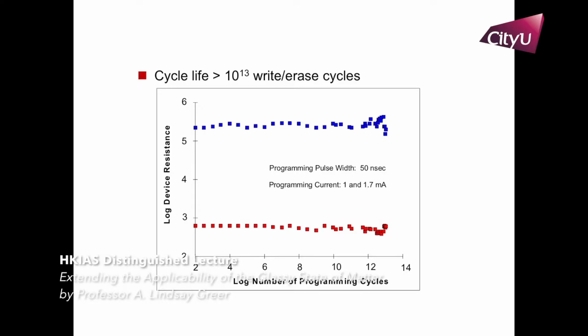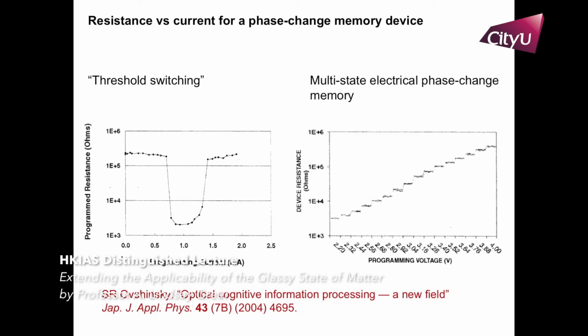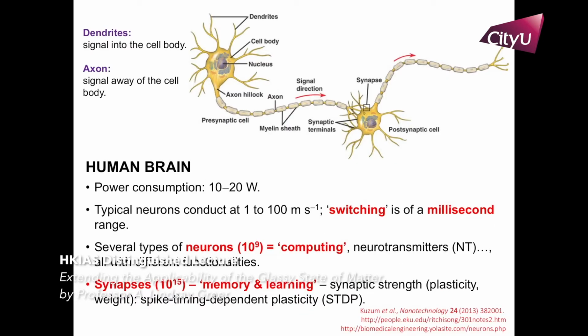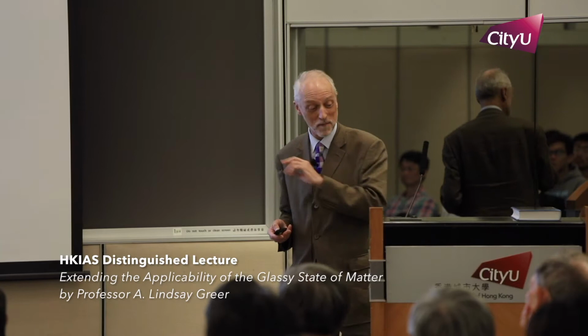I've said you melt, form the glass, crystallize the glass, you switch to and fro. How often can you switch it? Well, it carries on up to about 10 to the 13 reversals, so that's good enough. You don't have to go all the way between the resistance of the glass and the resistance of the crystal. They're nearly 2 orders of magnitude different. You could step to intermediate states in a given volume. That has excited a lot of interest because, of course, it's a little bit like our brains, where you get multiple signals coming in before you achieve the switching. So you have a sort of natural additive function in there. So people think of mimicking brain architectures in these chalcogenides. I think this is as yet rather exotic, but it's certainly much found in the literature.